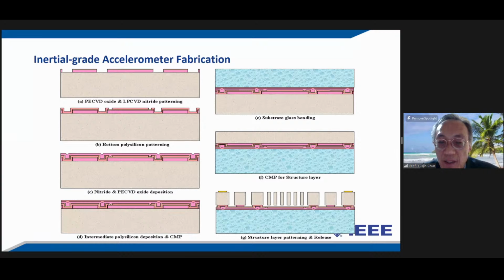And then on the right side, you put the glass bonding on top, which is green here, and then do the CMP for the structural layer, and then do the deep RIE etching, so that you can have a mass on both ends, and then anchored, and then the moving comb drives in the center. Okay, and then this comb drive is moving, to make an oscillation.